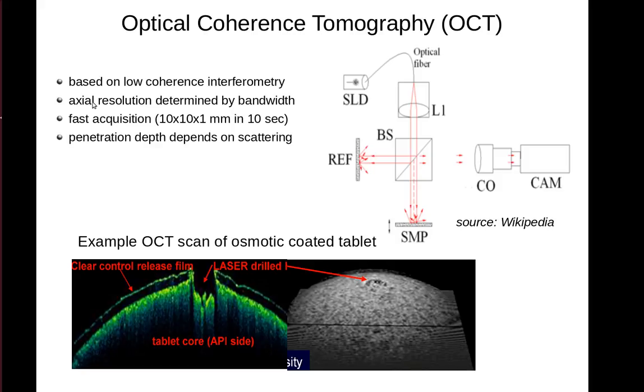The axial resolution is determined by that bandwidth. It has an acquisition time on the order of tens of seconds for a 10 by 10 by 1 millimeter sampling. And the penetration depth depends on the amount of scattering in the sample.